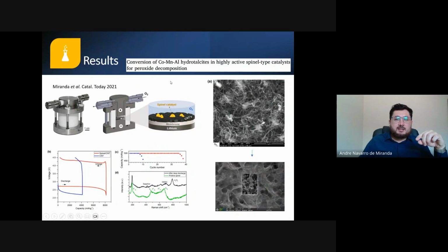So when we test the cell, we have here in blue the charge process, just using the carbon nanotube. And in red, we can see the carbon nanotube with the spinel catalyst. So you can see that it kind of doubles the capacity of this battery. And we also reduce it.